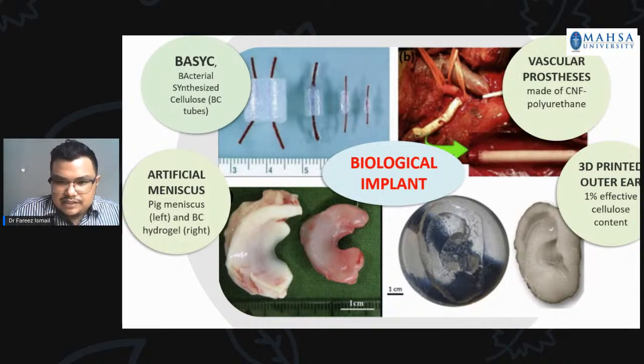This vascular prosthesis was placed between the brachiocephalic trunk and the right common carotid artery in a male patient. And it's also crucial that the nanocellulose materials have anti-thrombogenic properties to avoid blood clotting, especially when generating this kind of prosthesis. To achieve these anti-thrombogenic properties, endothelial cells have been used to produce a non-thrombogenic interface between the blood and the nanocellulose composite used in these implants. It can be either through inoculation of these endothelial cells onto the material itself, or through modification of the nanocomposite with features that can stimulate endothelial cell recruitment from the surrounding tissue. And as you know, endothelial cells make up the cell lining of the endothelium in the native blood vessel.